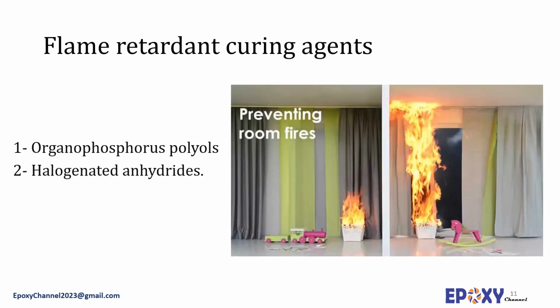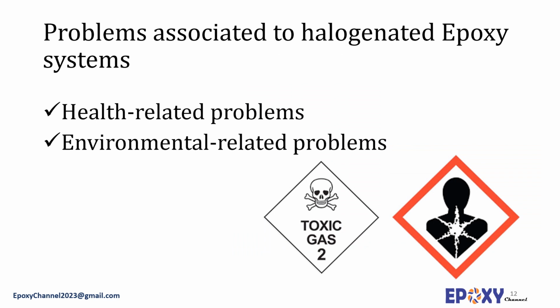Flame retardant curing agents for epoxy systems include organophosphorus polyols or halogenated anhydrides. Although the addition of halogenated flame retardants to epoxy resin matrices, such as tetrabromobisphenol A or TBBPA, is a fairly effective method to improve the flame retardancy of epoxy resins, upon combustion they produce a poisonous and corrosive smoke and can generate highly toxic halogenated compounds. Because of that, these resins are being phased out based on environmental regulations.